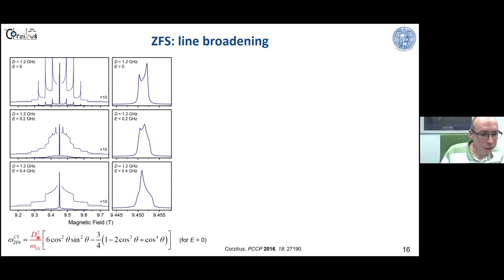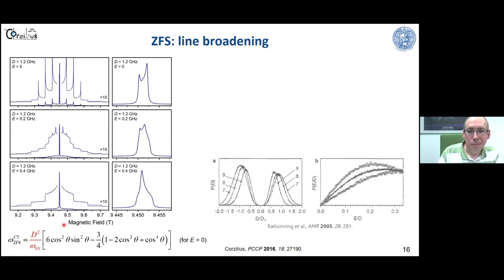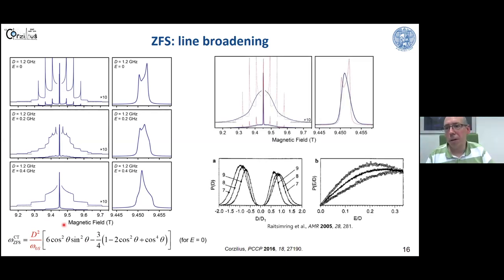because a second order effect also shifts the levels ms = -1/2 and +1/2 unequally. And this is proportional to the magnitude of the zero field splitting constant, divided by the Zeeman energy. And then in frozen solutions, you also have distributions of the D and E parameters, which have some kind of typical shapes.